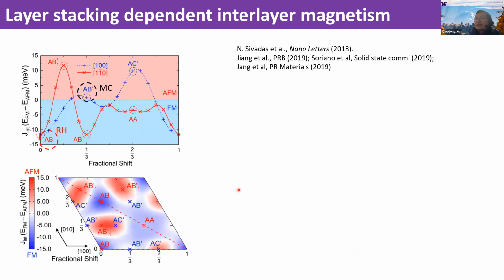An interesting property of these van der Waals magnets is that the interlayer magnetic coupling depends on the stacking order. There is quite a bit of theory work discussing how the interlayer coupling depends on the lattice translations. Here I just highlight work from my collaborator Di Xiao. You can focus on the bottom panel. He shows the energy difference between ferromagnetic and antiferromagnetic states as a function of layer translation. When you translate the two layers, there are regimes of ferromagnetic states and stackings corresponding to antiferromagnetic states.